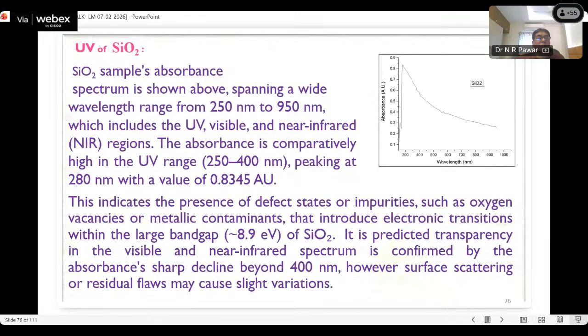Now UV of this synthesized material, and we are familiar with UV because this is a very common parameter. The spectrum is shown above, spanning a wide wavelength range from 250 nanometer to 950 nanometer, which includes the UV, visible and NIR regions, and the absorbance is comparatively high in the UV range, peaking at this value.